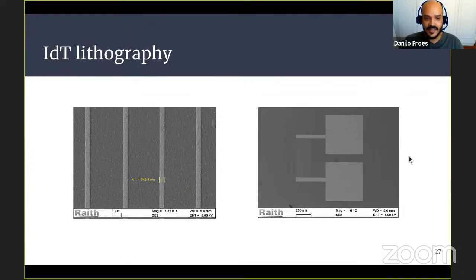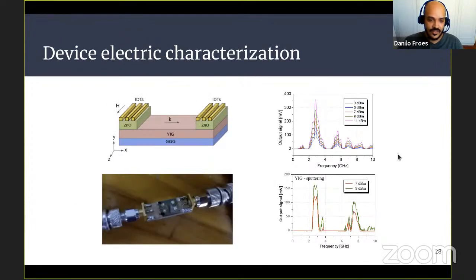After obtaining the final IDT, the interdigital transducer, we made this sample. This is how we built it. We got a GGG sample and deposited the zinc oxide with those proportions in these two separate islands. On top of these two separate islands, we did the lithography for the IDT transducers. Then we made the electrical contacts with silver glue. It was probably not the best, but here is an example of a sample we obtained.